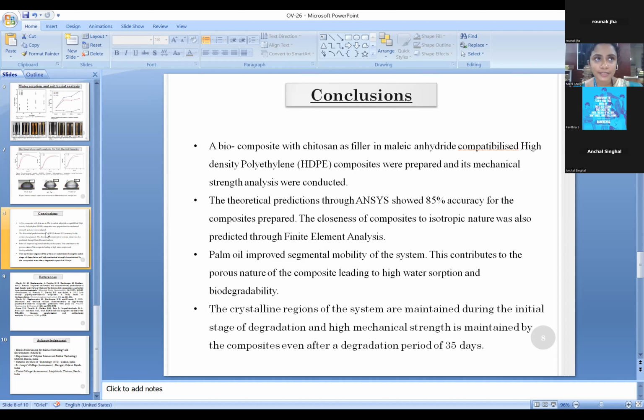when we're adding palm oil to the system, there's a high relaxation of the polymer chains. That is, the palm oil can improve the segmental mobility of the system. So I have worked on positron annihilation lifetime spectroscopy studies also. In the studies, it was shown that a large number of pores was formed in the system when palm oil was added. That is, the number of pores which are having very small sizes is very high in the palm oil added system. So it is mainly because of the segmental mobility caused by the palm oil in the system. So it is leading to the high water absorption and biodegradability.